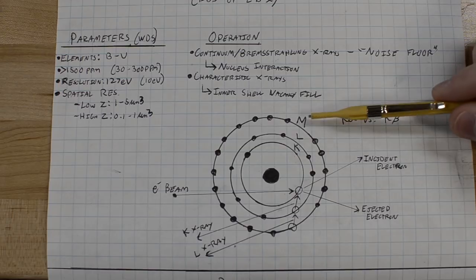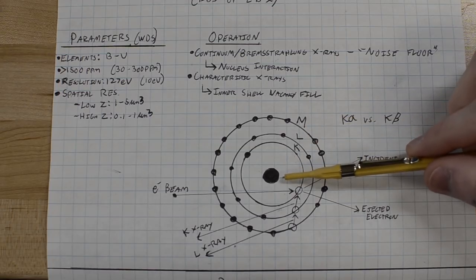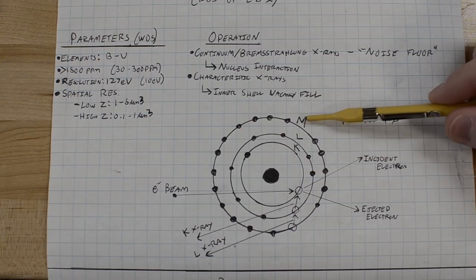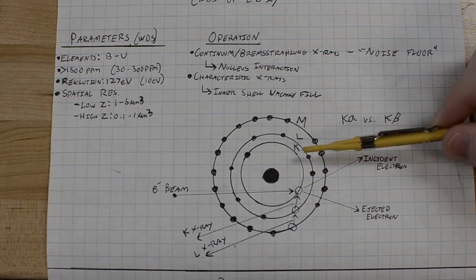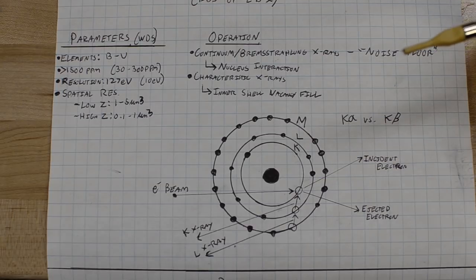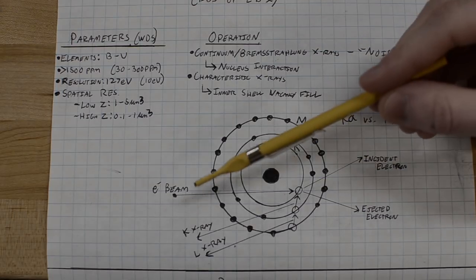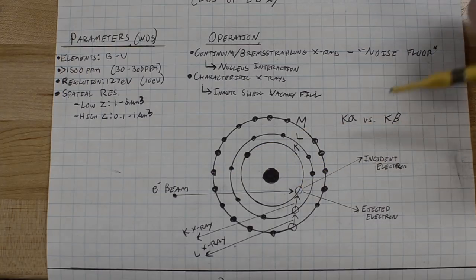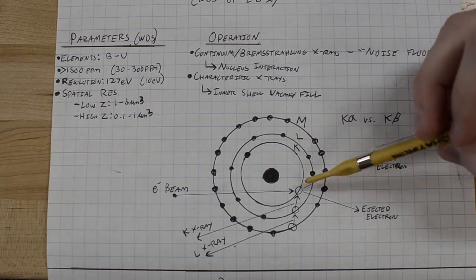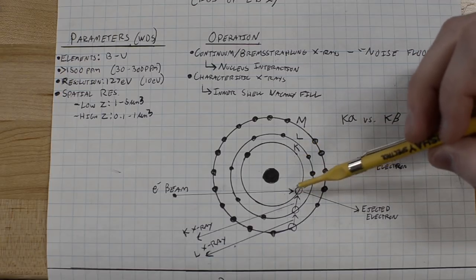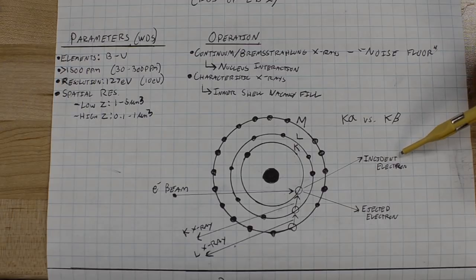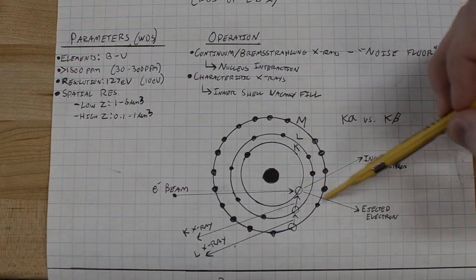They'd like to be closer to the nucleus. The M shell, because it's the furthest away, has the highest potential energy. It has the highest physical distance that it can fall into the nucleus and therefore has a higher energy associated with it. When an energetic electron beam hits the sample, it can sometimes knock out an inner shell electron. From here, we're knocking out this K-shell electron.